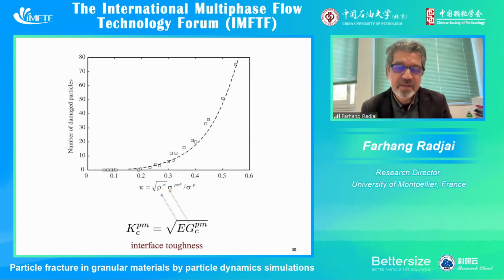What I'm interested in is this curve and the next one. Here we have calculated the number of damaged particles during tensile loading. And we have shown that actually the data for the number of damaged particles, which is something which can be measured in practice, is controlled by something which we call interface toughness. So we can define a toughness, based on rupture mechanics concepts. And we find that in general, the toughness combines the amount of the matrix and also the adhesion. Both contribute to the toughness, and this toughness controls the damage of the particle. So it's interesting. And it is true both in quasi-static and in dynamic, because the grinding process is quite dynamic.